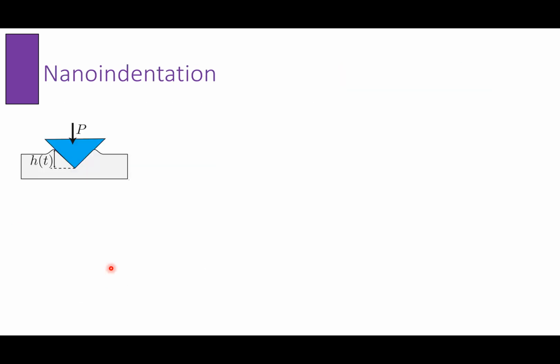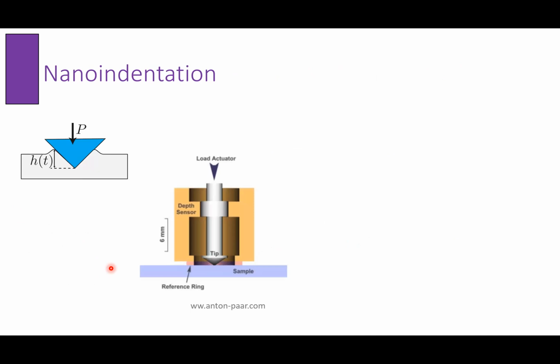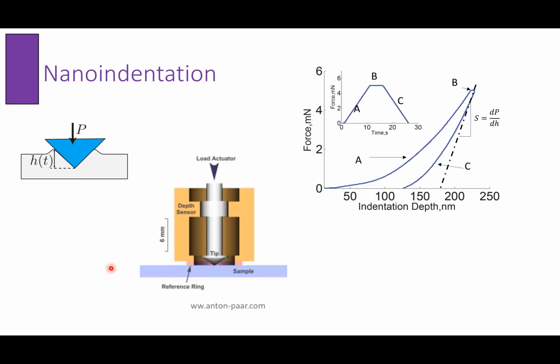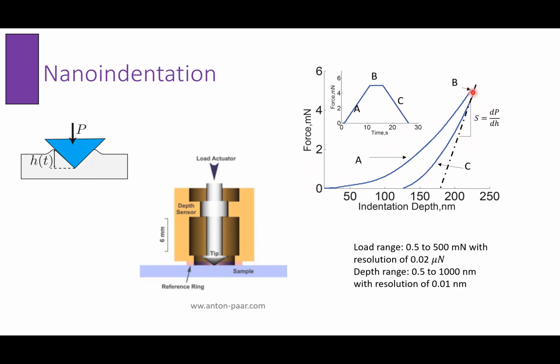Another method that we're using to probe the behavior within the context of CO2 sequestration is going to be nanoindentation. The principle of nanoindentation is you're going to have a probe, and then you apply the force. Typically, you're going to hold the force constant and unload, and you're going to record the force. You increase the force, then you hold constant and you unload. During the unloading, you have this unloading slope that is going to give you the indentation modulus, and the maximum penetration depth is going to give you the indentation hardness.